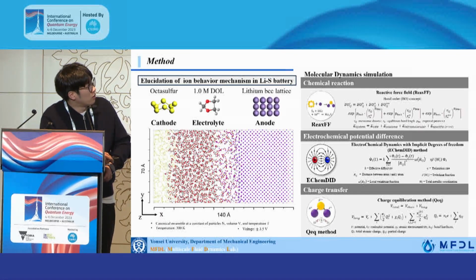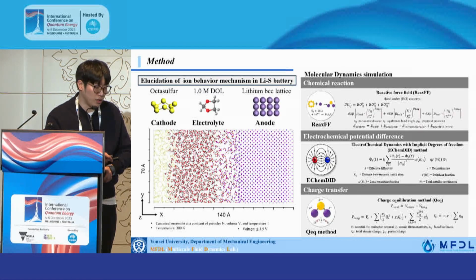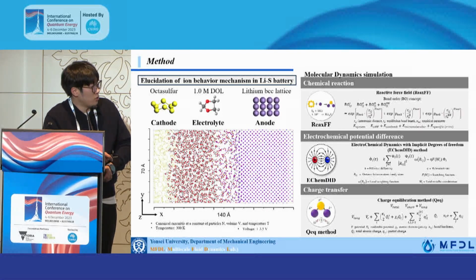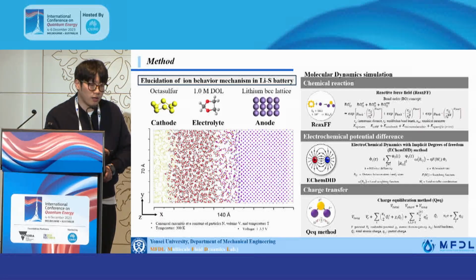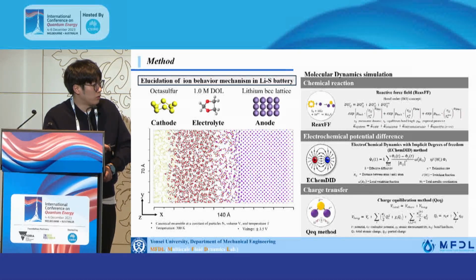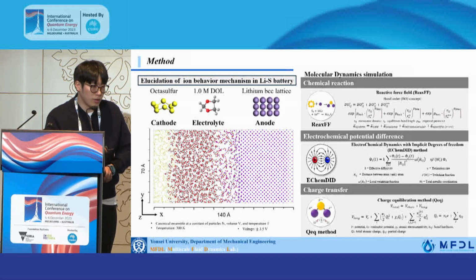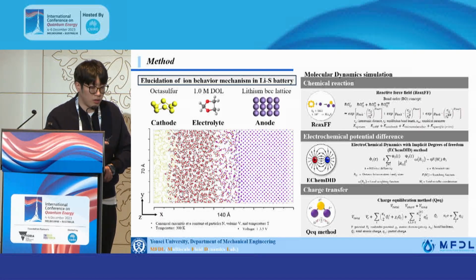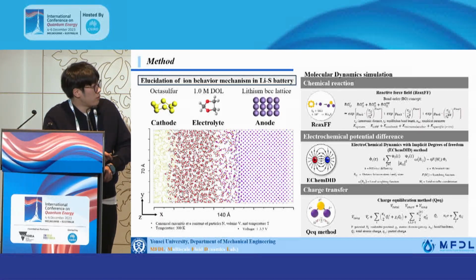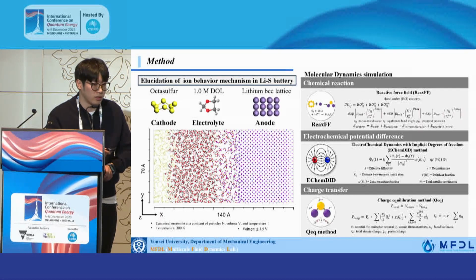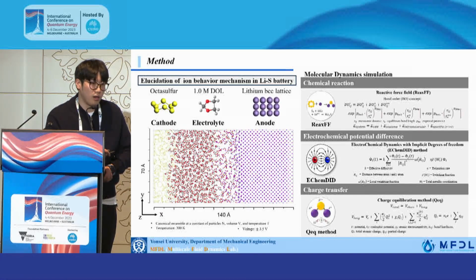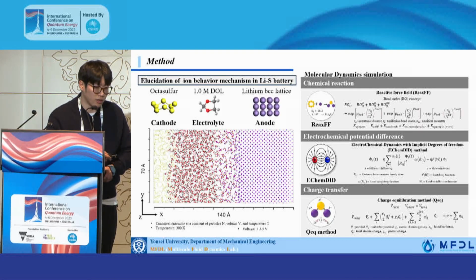The first method is the reactive force field that can model the bond breaking and formation. So we can use this method to implement the electrochemical reaction in the simulation. And the second one is the EChem-DID method, which can calculate the voltage propagation and voltage equilibration. So we utilize this method to apply the repeated voltage on the electrode. And the third one is the charge equilibration method, and this method can calculate the charge distribution and charge transfer in the system. So by using this method, we can model the oxidation and reduction reaction in our system.